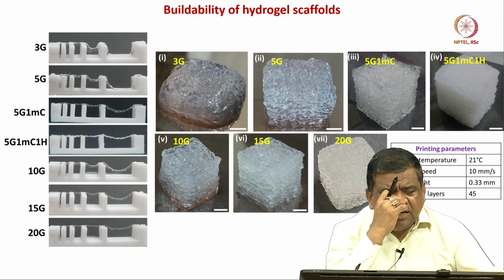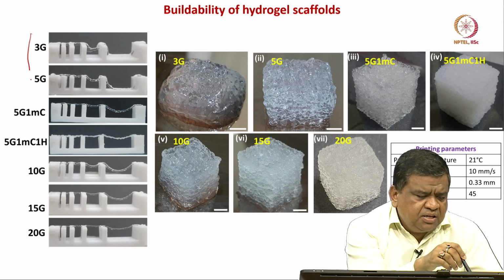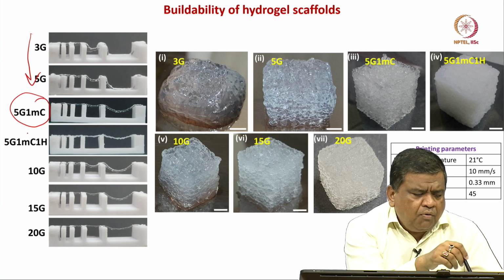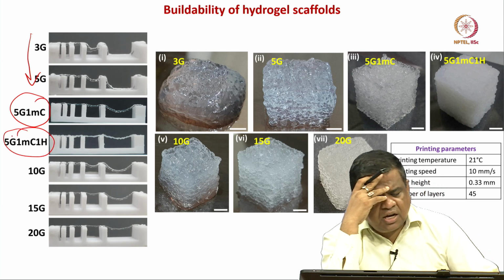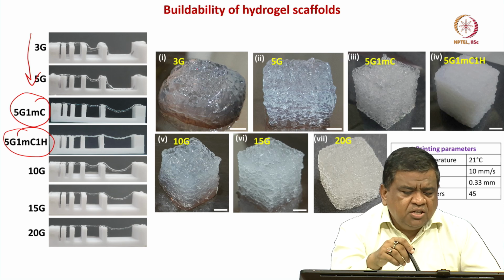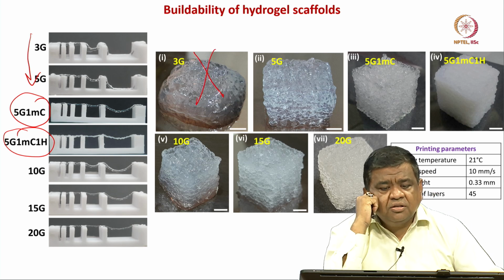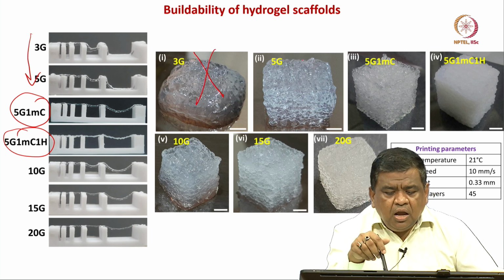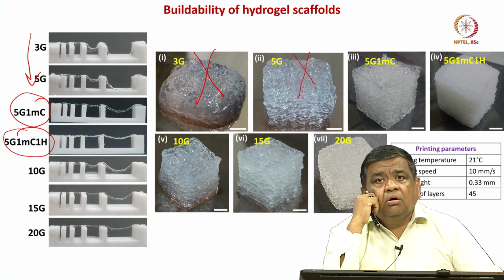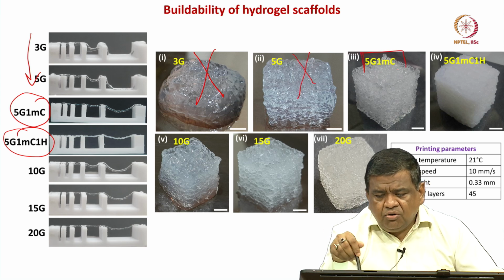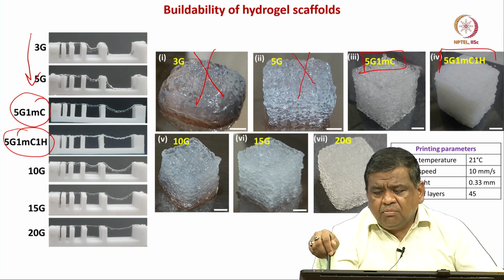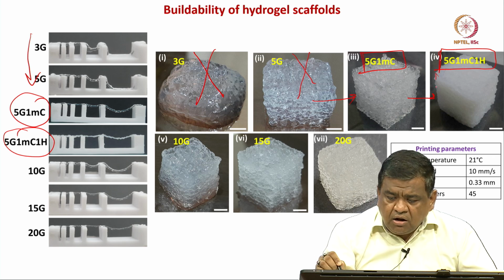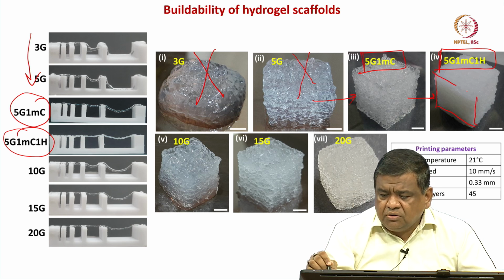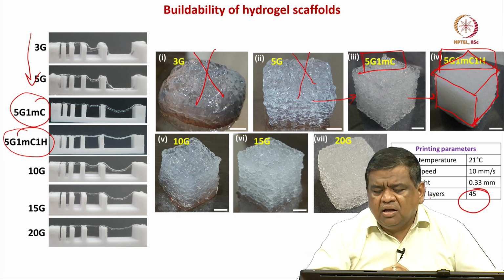Now, when you see that 3% Gelma goes to 5%, and then you also add 1% carboxymethyl cellulose and 1% hydroxyapatite, 3% Gelma is no good, right, because there is no shape fidelity. 5% Gelma is also no good, but when you add carboxymethyl cellulose and further you add hydroxyapatite, you can see that color and appearance also change, and you can go up to very large structures, right, and you can go up to 45 layers of the structures.